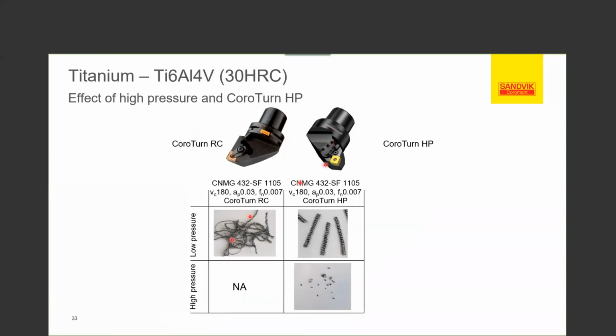And you can see here using the standard or low pressure, we'll call it, and using high pressure. So the material here we're actually machining is titanium 6Al4V. And you can see here the types of chips you're going to get using standard pressure as opposed to the high pressure you're using here. So if you're having trouble with the bird's nests and things of that nature in the titanium, using high pressure upwards of about 80 to 100 bar will work wonders for you. It works better with titanium than nickel materials, but it still will help with the nickel materials.